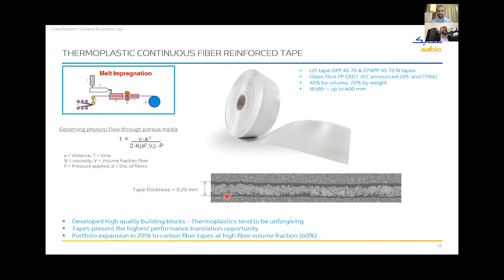And I show you a cross-sectional micrograph of such a tape. This is the one that we work with Giles's group here quite heavily, showing the good dispersion of the fibers across left to right, as well as good impregnation with very low void content inside the fibrous media. And why is that important?